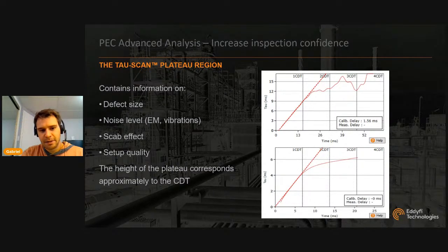If you see the tau scan, especially the calibration tau scan, end before 3 CDT, that means that the A-scan window is too short. That would happen typically if you do your smart pulse and then recalibrate on existing areas with a thicker wall thickness, then you'll see that tau scan calibration get under 3 CDT. Typically, we recommend recalibrating, redoing a smart pulse in those cases. You want your tau scan to last between 3 and 4 CDT, especially for the calibration.